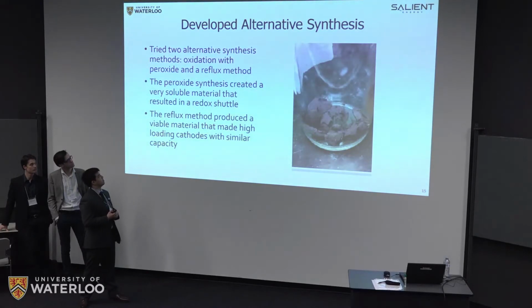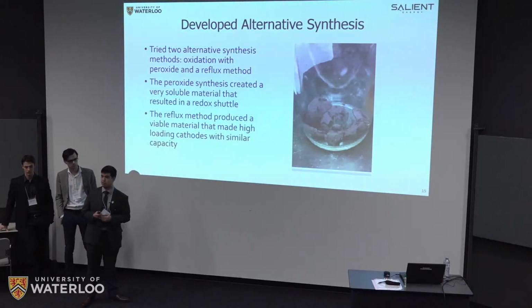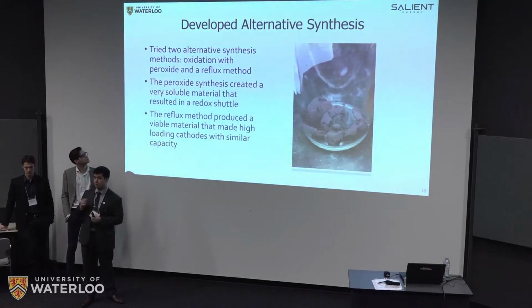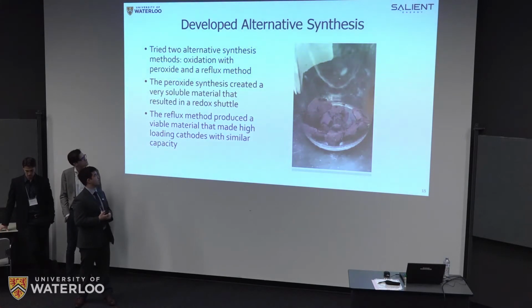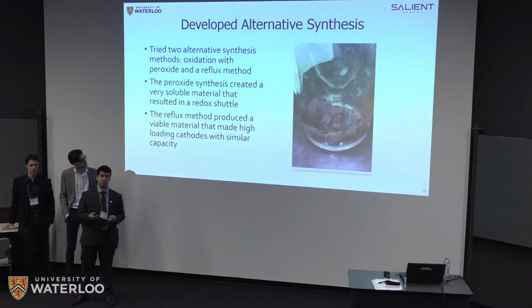One other thing that our FYDP group did is that we developed an alternative synthesis by testing out two alternative methods. One of them was oxidation with peroxide, and the other was a reflux synthesis. Unfortunately, the peroxide oxidation method resulted in something called a redox shuttle, which means that when the cathode dissolved in the water-based electrolyte, it would basically charge forever, which obviously doesn't make for a very good battery. The reflux method, on the other hand, produced a more ideal case in which the cathode was non-dissolving in water. So that was good.